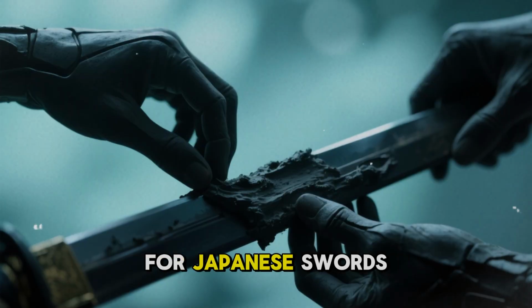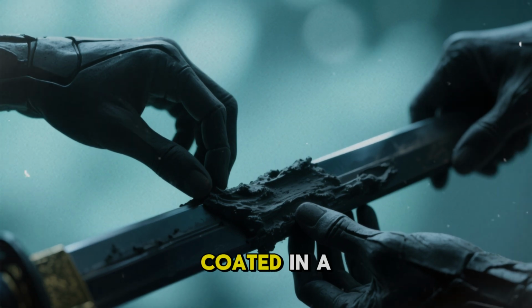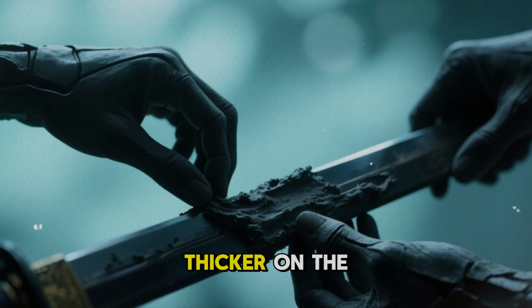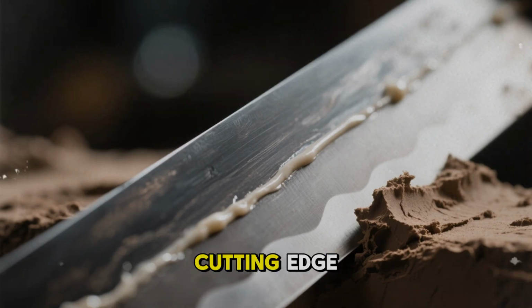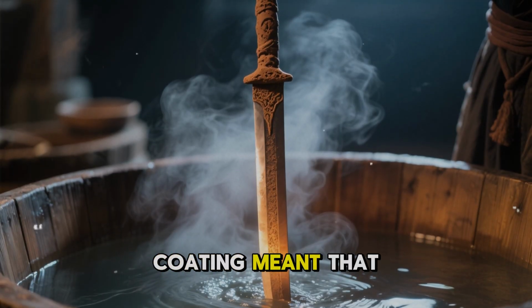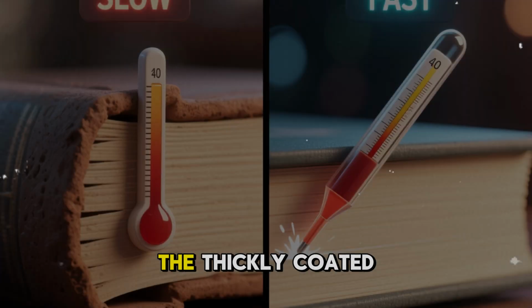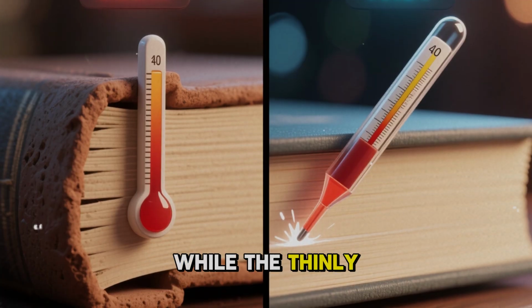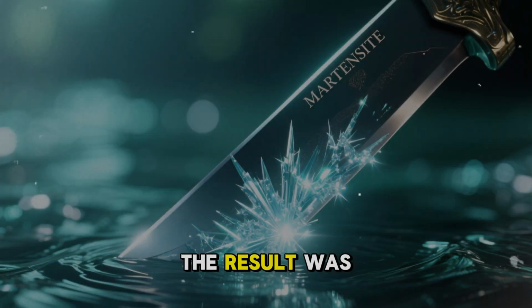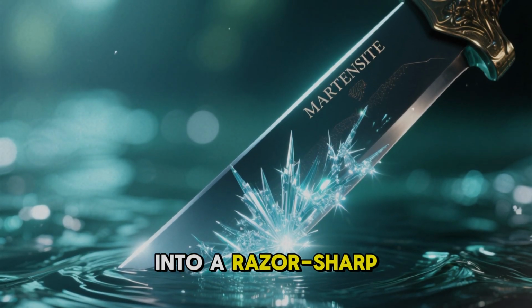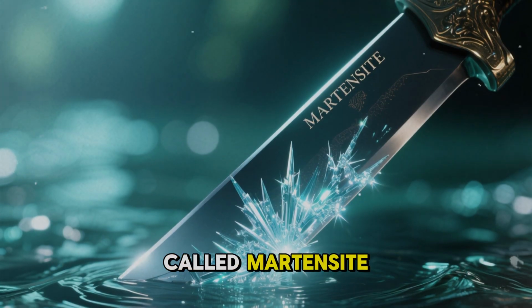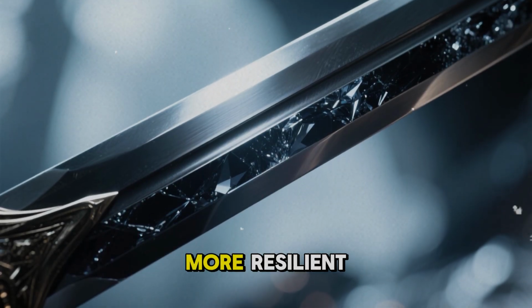point. For Japanese swords, the blade was first coated in a carefully applied layer of clay paste, thicker on the spine and sides, thinner on the cutting edge. This differential clay coating meant that when the blade was plunged into water, the thickly coated spine cooled slowly while the thinly coated edge cooled almost instantly. The result was a blade with the edge hardened into a razor-sharp crystalline steel structure called martensite, while the spine remained tougher and more resilient.